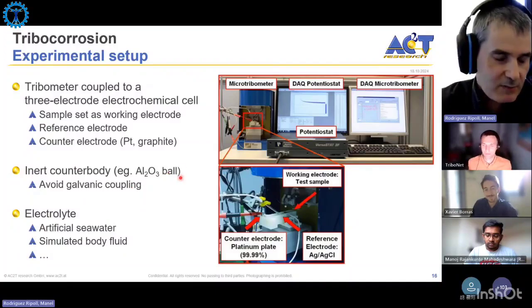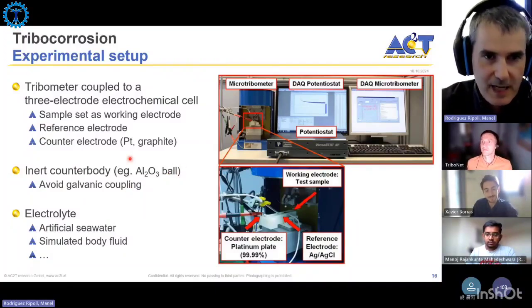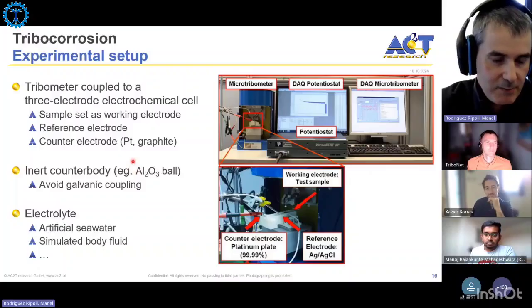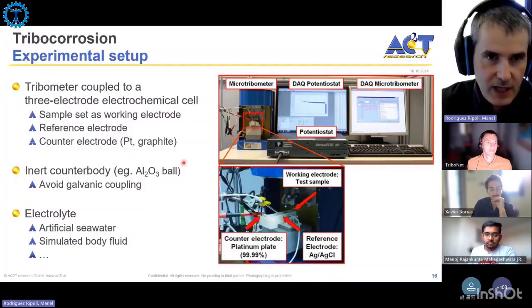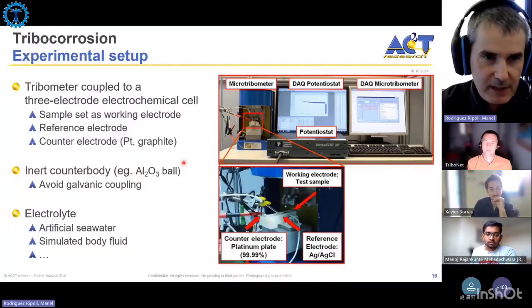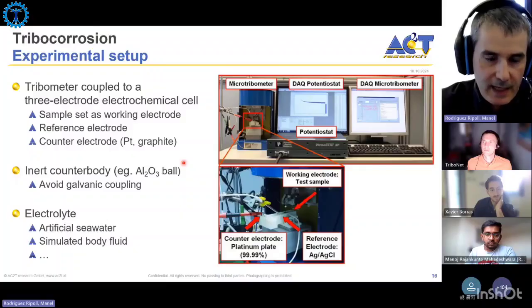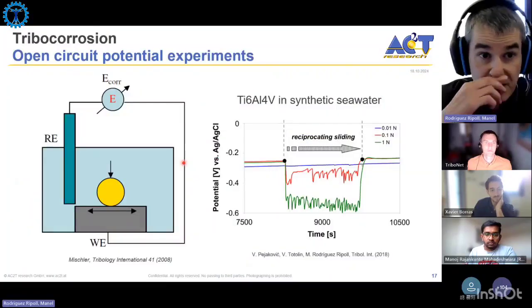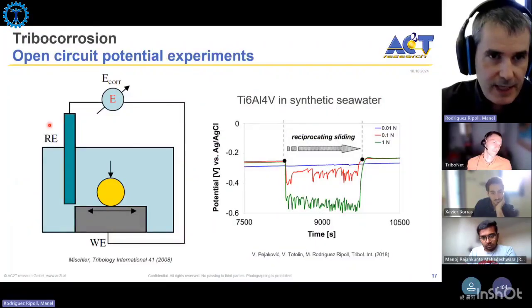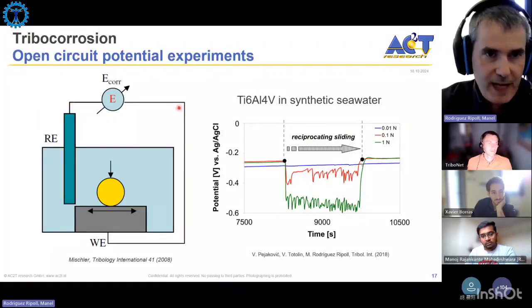So that's why it is very often preferred to have an aluminum oxide ball. It's not a must, but it's much easier to interpret the results if you have an inert counterbody that is also not participating so much in the damage, because it will typically not wear. And if we do something like this, in that case, if we have only 2 electrodes, we don't need to apply any voltage.